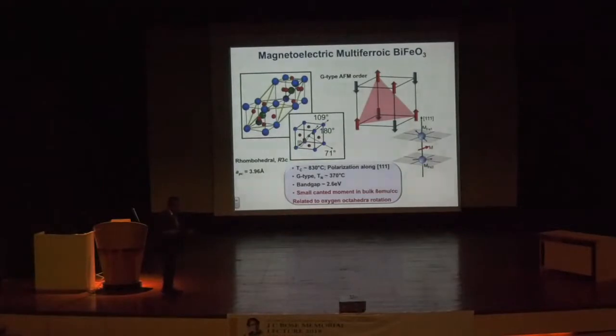It turns out that because of something called the Dzyaloshinski-Moriya coupling, an antisymmetric coupling, you have a very small canted moment of the order of about 8 emu per cc. Now, if this moment had been 50 emu per cc, which is very difficult to do with just Dzyaloshinski-Moriya coupling, if it had been 50, this material would already be in technology. Unfortunately, 8 is just a little bit too small to be useful. Therefore, you have to do some materials manipulations to get to something that's technologically useful. Okay, so this is perhaps 80% of the entire field of multiferroics. There have been about 20,000 papers still going, people still publishing papers, including myself, and we, in some sense, published one of the early papers.